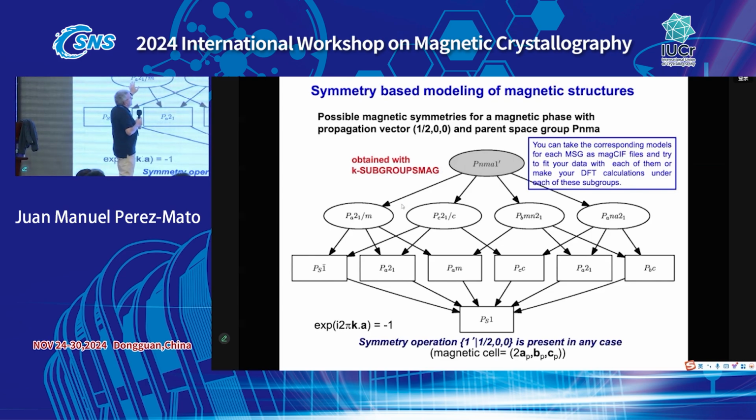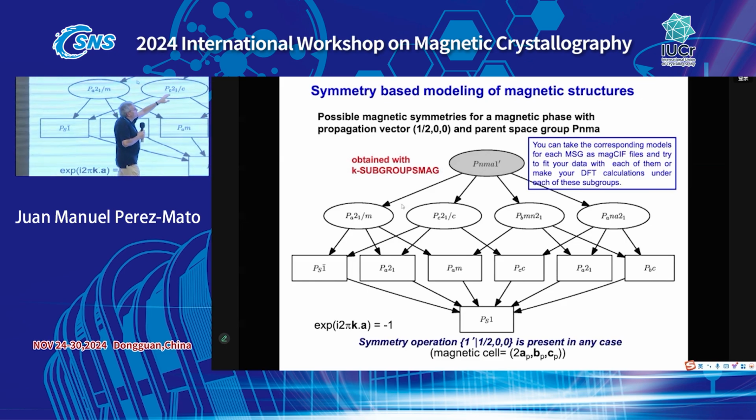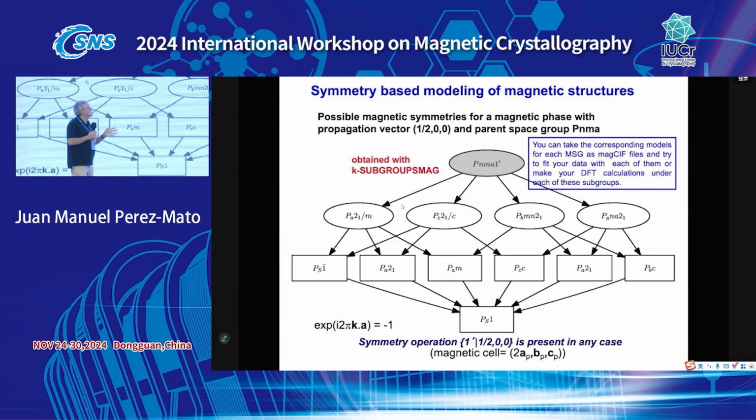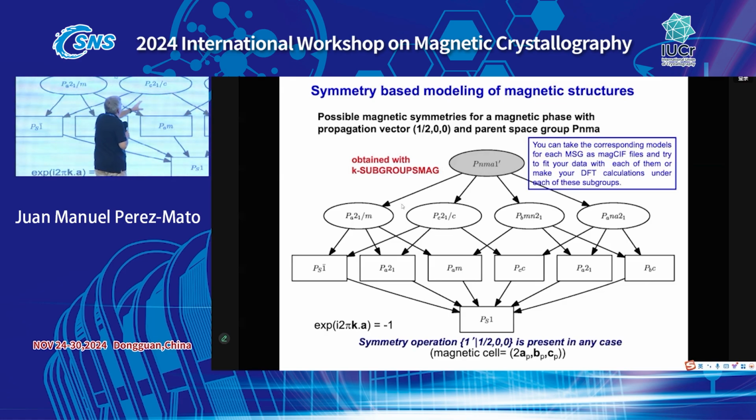And the point is that you have what we call a group-subgroup structure where one can distinguish 4 maximal symmetries. Of course, there is no theorem telling you that my system should stay in a symmetry corresponding to these 4 possibilities of maximal symmetry, but this is the practice. Empirically, most of the systems just get magnetic orderings according to very high symmetries, corresponding to the wave vectors that you have seen. That's what we call K maximal symmetries, K from the K vector, and in this case, it will be these 4 here.